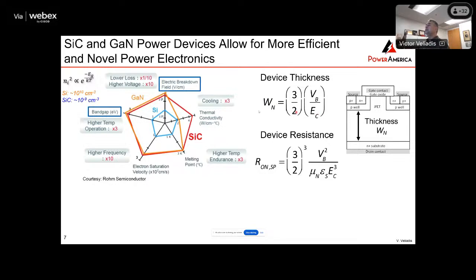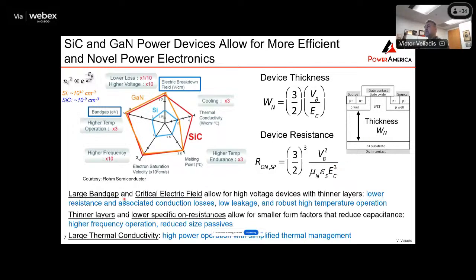So if your critical electric field is 10 times higher, as it is compared to silicon, then the thickness of your device for the same voltage capability becomes 10 times thinner. If you look at the resistance of this thick layer, which for high voltage devices is the major contribution to resistance, you can see that it's inversely proportional to the third power of the critical electric field. So if the critical electric field of your material is 10 times higher than silicon, then this drops the resistance by 1,000 times. So we have large band gap and large critical electric field in silicon carbide as well as GaN, and that allows for high voltage devices with thinner layers.